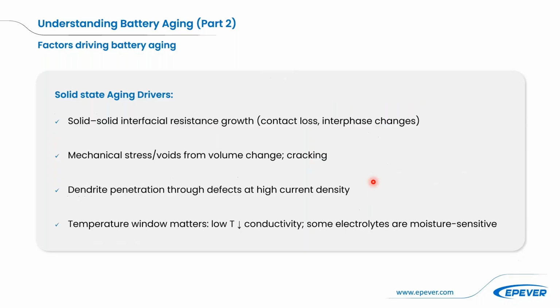And for solid states, the architecture is different, so we have different issues here. Over time, you can see interfacial resistance creeping up, or mechanical voids and micro cracks as electrodes breathe in and out, shall we say. And under high current density, dendrites can still find their way through defects.